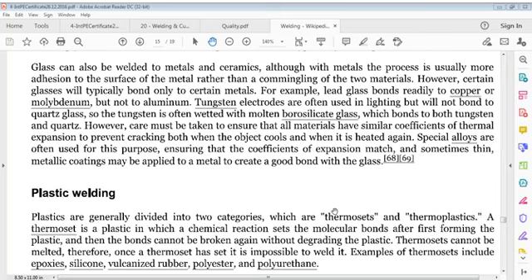Tungsten electrodes are often used in lighting but will not bond to quartz glass, so tungsten is often wetted with molten borosilicate glass, which bonds to both tungsten and quartz. However, care must be taken to ensure that all materials have similar coefficients of thermal expansion to prevent cracking, both when the object cools and when it is heated again.